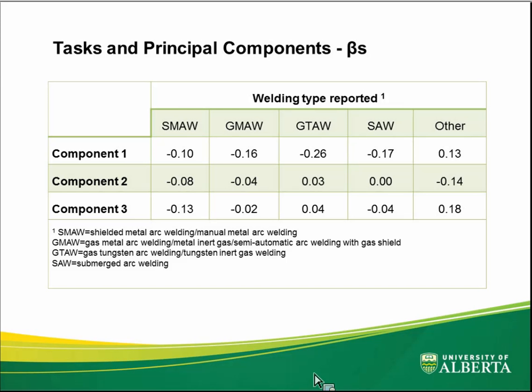So the model that was supported in the principal components had 3 components, and I'll try to briefly explain. You can create a component score for each person by weighting the urinary metal concentrations by the loading factors in the bottom half. But what we can see is that all the metals are positively loading, or positively contributing, to the component score for component 1. And in component 2, there's a contrast. So cobalt and manganese are negatively impacting that component score, in contrast with zinc, which positively contributes to that component score. So it allows us to look at how all of the metals can contribute to a single score, and then we can use that score instead of the urinary metals individually. So then that's what we did next.